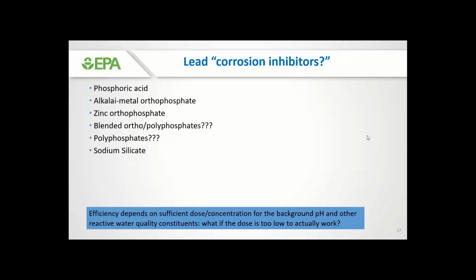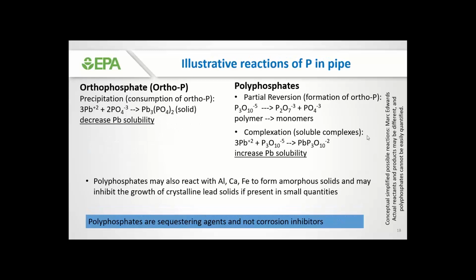And I have question marks there next to polyphosphates, and I'll talk about that in a little bit. But we also have corrosion inhibitors that are not phosphate-based, such as sodium silicate. It is important to pick the right type of corrosion inhibitor, and even then, the appropriate dose will depend on the underlying water chemistry, the background pH, alkalinity, the reactive water quality constituents, so that the dose that we're using actually works.